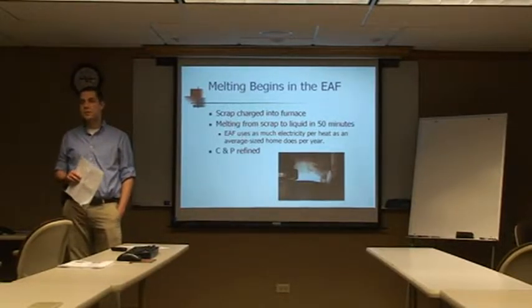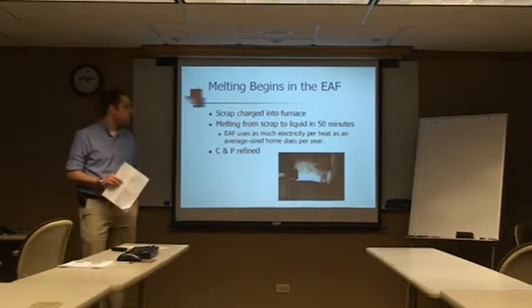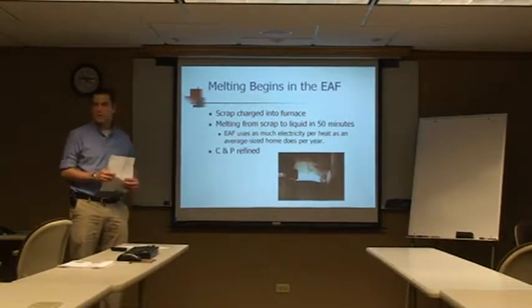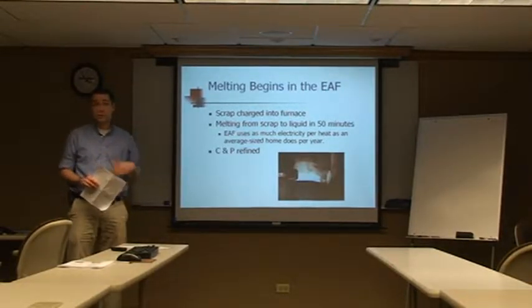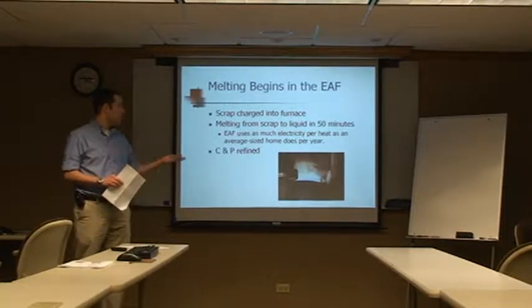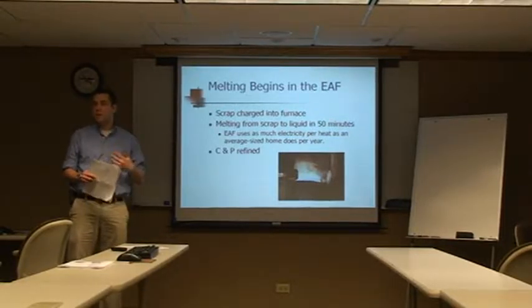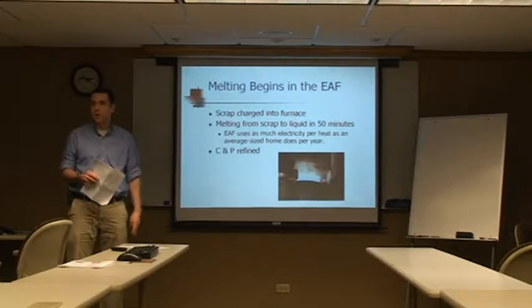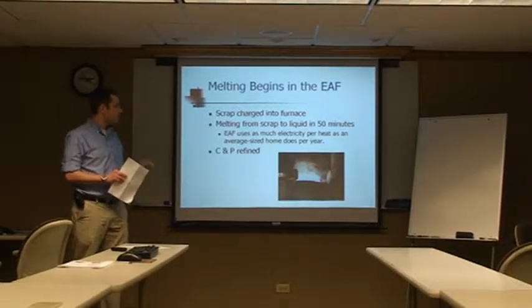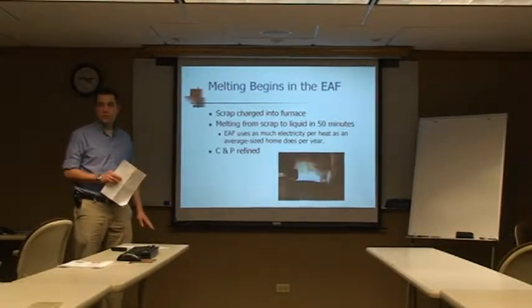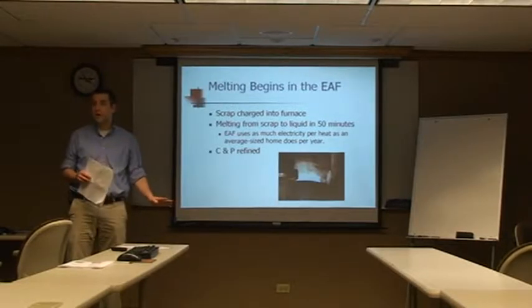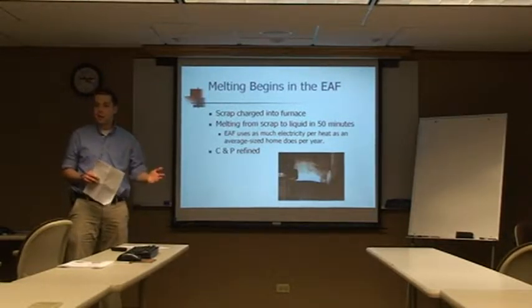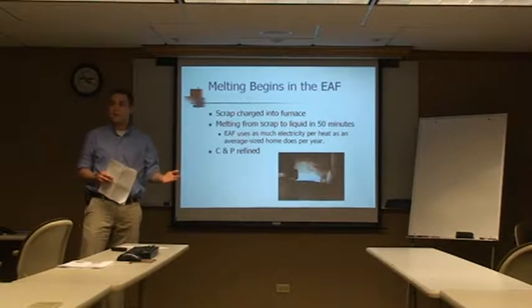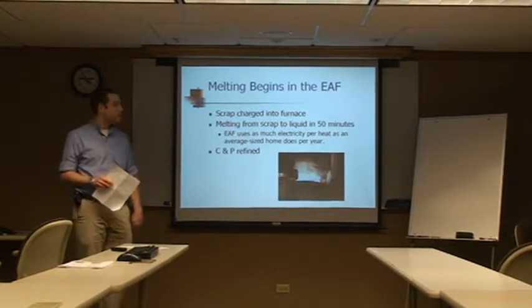Yeah, there are different levels of arc furnaces. The one we have at EQS is one of the higher levels, which enables us to get in 50 minutes. If you had a lower level arc furnace, it would take you a little longer. Plus, we also streamline things in that we use our arc furnace purely to melt scrap. We don't try to do any alloying in there. We do that later on down the line, so that also helps with the efficiency.